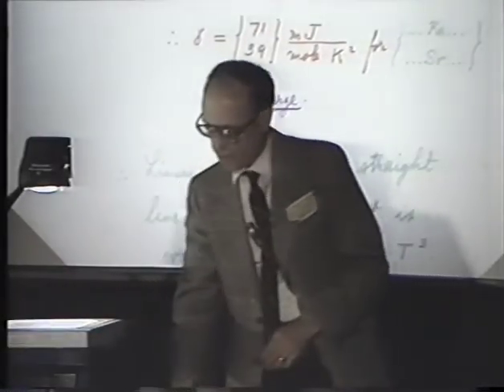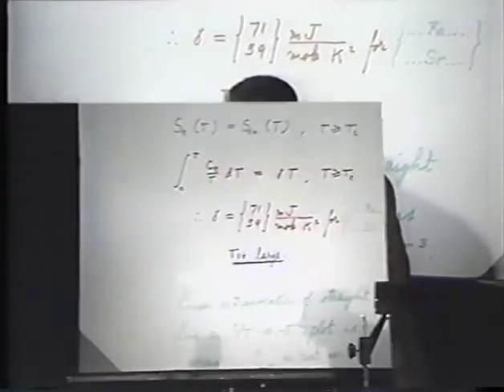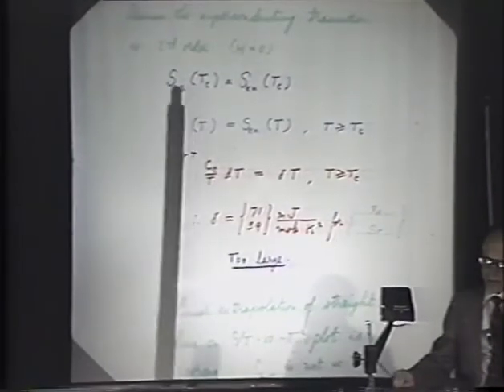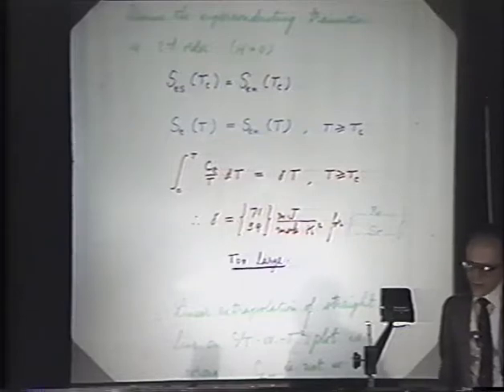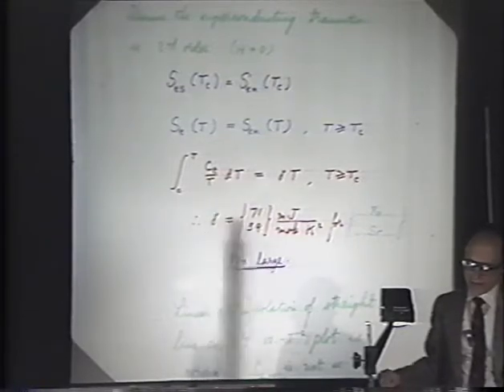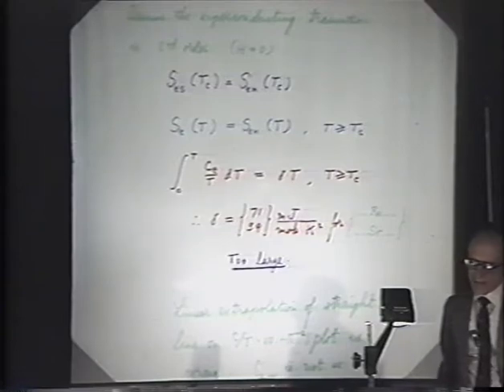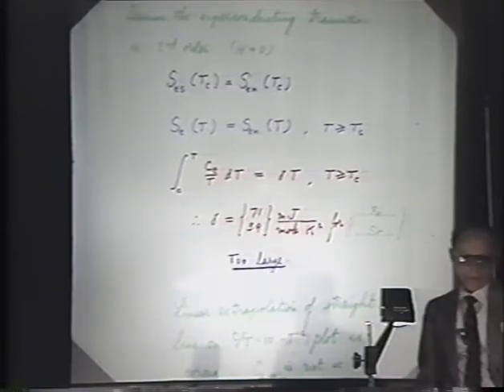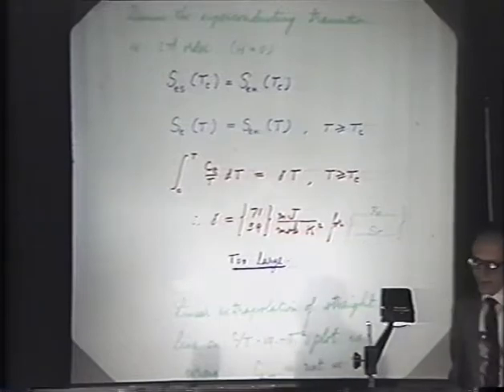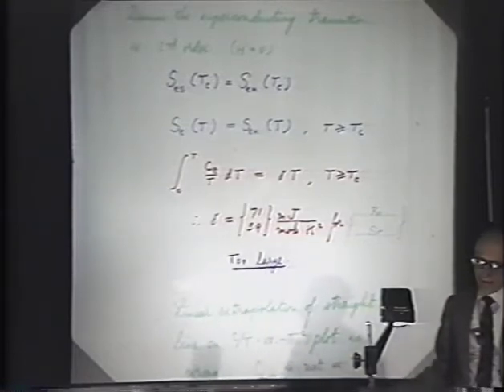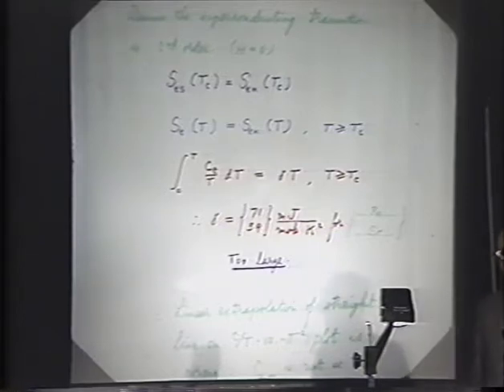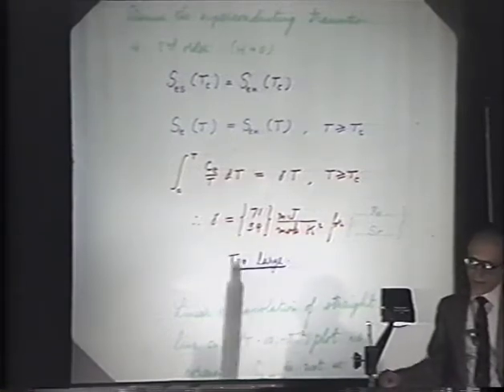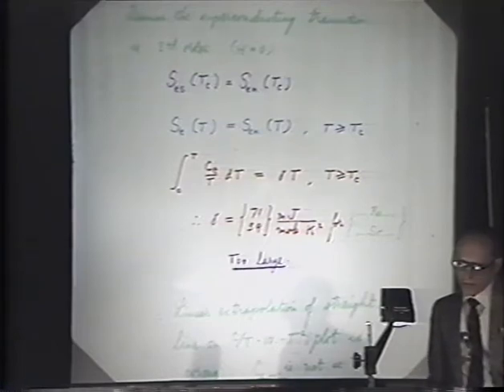Now we assume here that we have a second order transition to the normal state, and so the entropy at the superconducting transition temperature has to be equal to the entropy of the normal state. So if we integrate C over T dT, where C is the electronic part of the specific heat, we should get gamma T, and that gives us a value of the electronic specific heat coefficient gamma. The result of this is that the gamma values we get are about an order of magnitude too large, according to, for instance, critical field data acquired at Iowa State. They get around 5 or so millijoules per mole degrees squared.